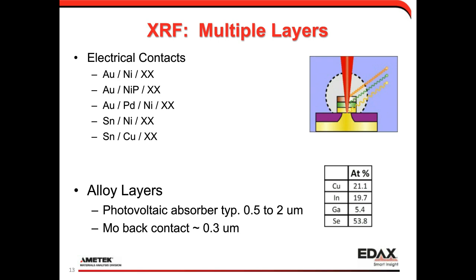Another example of alloy layers, in the photovoltaic market, you typically have some sort of photovoltaic absorber layer. It's important to know what the composition of that is because it affects performance of the system, as well as you may have an electrical back contact. So the typical measurement would be to measure the thickness of the absorber layer as well as its composition, and then the thickness of the electrical back contact as well. And you can do this kind of thing with XRF also.